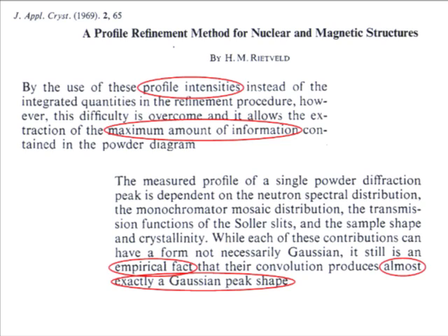So basically we have two types of parameters in Rietveld refinement. One type has a sound physical basis. Another type is empirical, and I think this is the problem why Rietveld refinement doesn't work in all cases, especially when we have violation of translational symmetry.